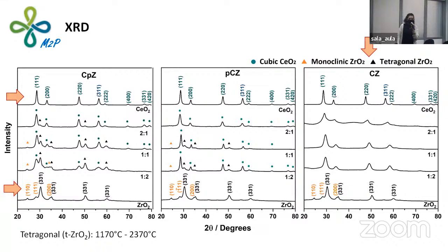We can see that for CPZ and PCZ, there are peaks of both ceria and zirconia, showing that we have both oxides in the composition, while for CZ, we don't have the specific peaks of ceria and zirconia. We have intermediate peaks between ceria and zirconia, showing that we achieved here a solid solution as expected.